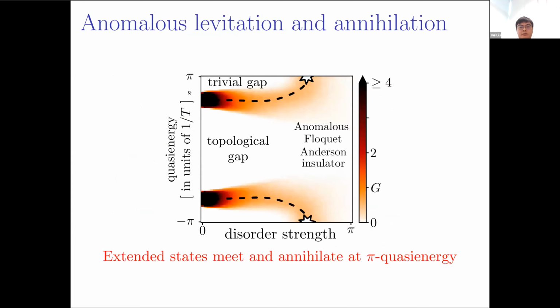This anomalous process can be described by this figure. When the disorder is increased, these two extended states carrying opposite topological invariance move towards each other at pi quasi-energy. So in this process, the topological non-trivial gap at 0 quasi-energy will become larger and larger and expands in the whole quasi-energy spectrum, which give us anomalous Floquet-Anderson insulators. So even in the maximum disorder strength in the Floquet system, we will still get a topological non-trivial phase.